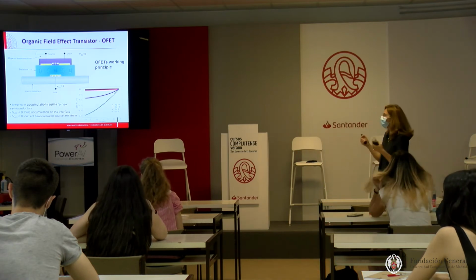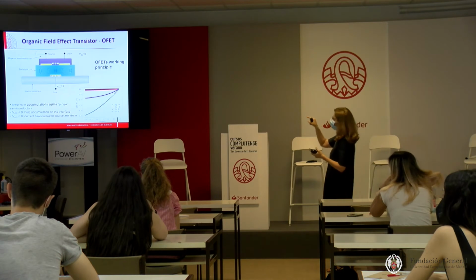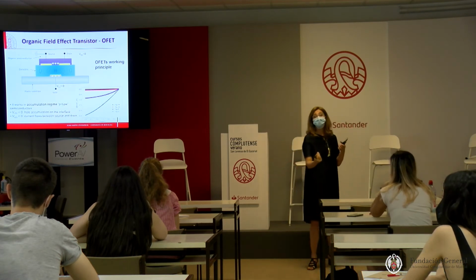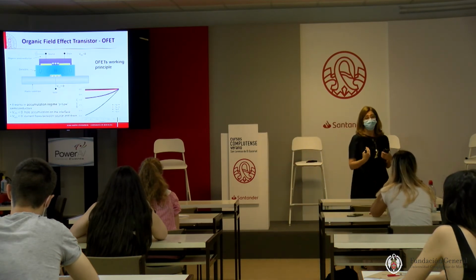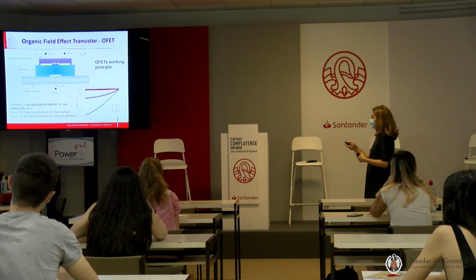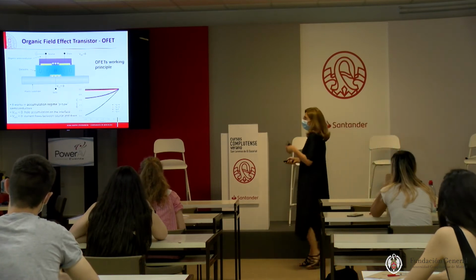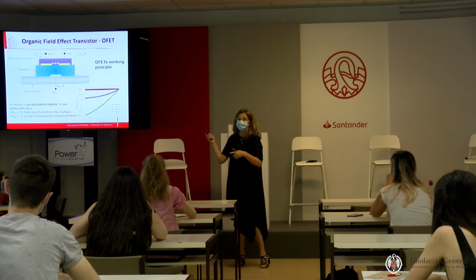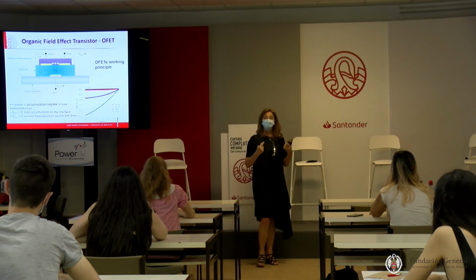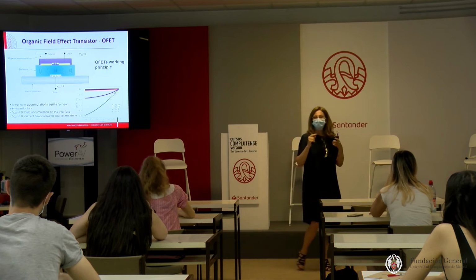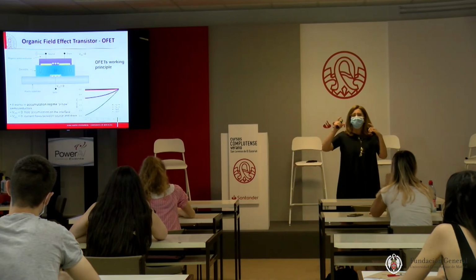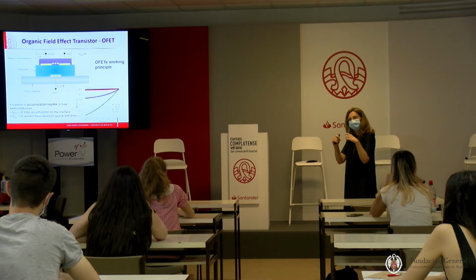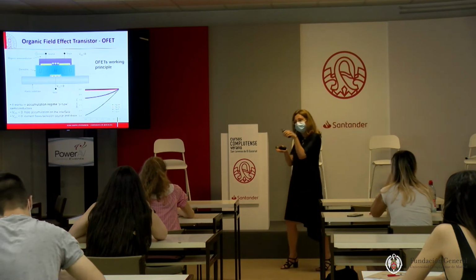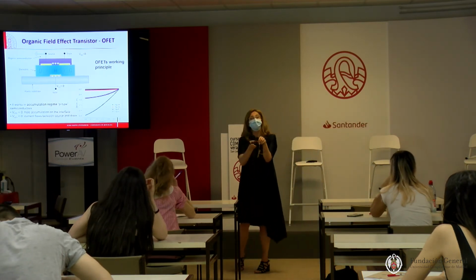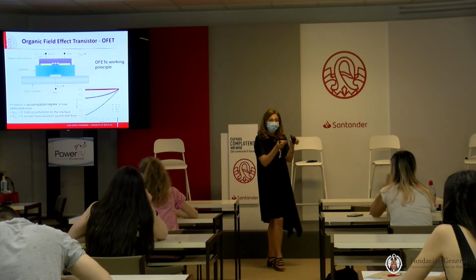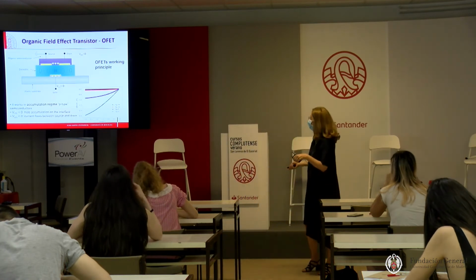So basically, you can enhance the transport in the semiconductor by applying a gate that attracts more charges in the channel. That is called accumulation mode. Why am I telling you this? Because it tells you that in order to have a good operating organic field effect transistor, you don't need a very thick material, because everything happens at the interface between the organic semiconductor and the dielectric. And that is one of the big strengths of these materials.